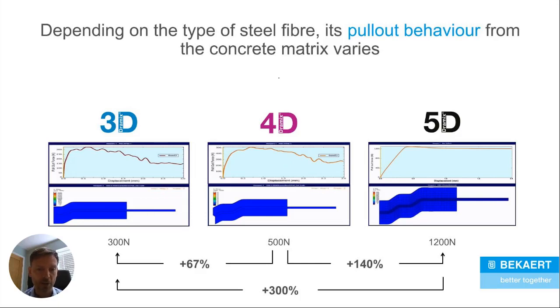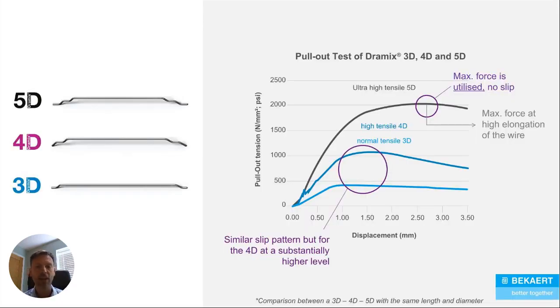What happens to the straight part of the wire is the yield will occur there, but in order to stop that fibre from snapping, we use an ultra high tensile grade of wire of 2,300 newtons. What that wire does is it has an elongation capacity, so it has a certain percentage allowance to actually allow that fibre to stretch without breaking. So the failure mode of Dramix 5D is completely different, and that gives us different ductility values because of that. Here we can see the effect of the pull-out test, the sort of wire that we make these fibres from, okay?